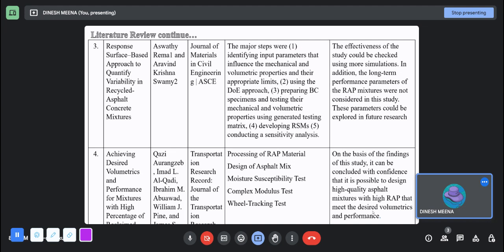Response surface based approach to quantify variability in recycled asphalt concrete mixture. The major steps were identifying input parameters that influence the mechanical and volumetric properties and their appropriate limits, using the DOE approach, preparing BC specimens and testing their mechanical and volumetric properties using generated testing matrix, developing RSMs, and conducting a sensitivity analysis. In this, the effectiveness of the study could be checked using more simulations. In addition, the long-term performance parameters of the RAP mixture were not considered in this study. These parameters could be explored in future research.